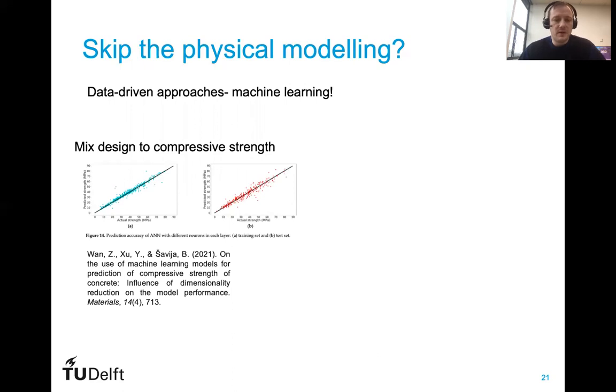So we have performed some calculations and developed some models that are able to relate the mix design and compressive strength of concrete materials. There is a widely available data set that we use to train and validate our different machine learning models. And we showed that different models can be used with different success to relate the mix design and the compressive strength. What we also observed, which people usually don't report, is that if you change the data set and you try to use your model on data that it hasn't been trained on with a different distribution, the model doesn't really work. So it is important to use the same distribution of data to train the model and to validate it later on. If you don't do that, the model will not be successful.